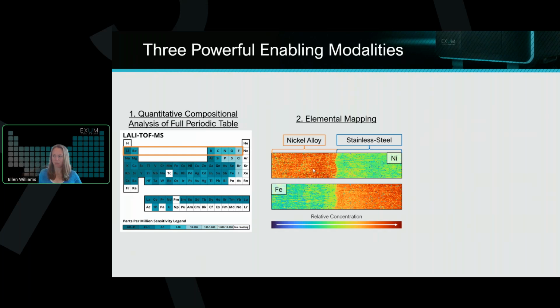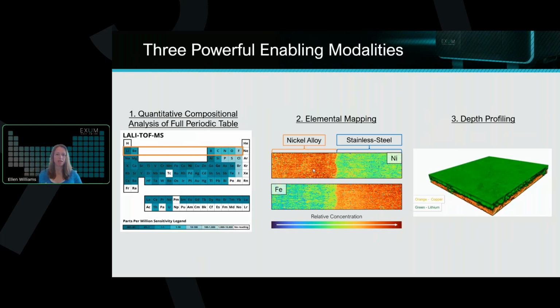resolution smaller maps. And then because we're actually ablating or removing material, we can create a three-dimensional depth profile by repeating that elemental mapping process layer by layer, removing material. There's again a lot of versatility on the resolution of the depth profiles as well, because the user can change the laser power to either remove more or less material. So if you blast it with a lot of power, we can remove up to microns of material per layer, or if we dial the power back, then we can remove as little as tens of nanometers per layer to create depth profiles of different resolutions depending on the application.